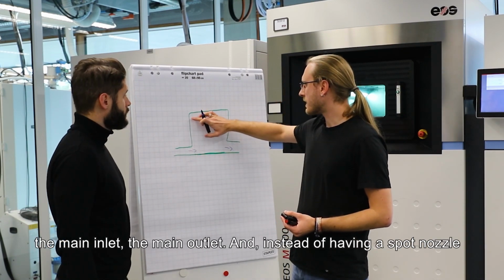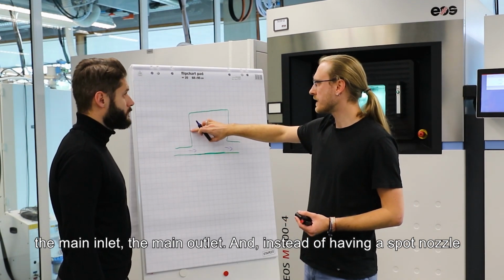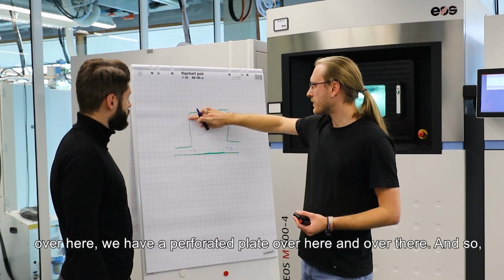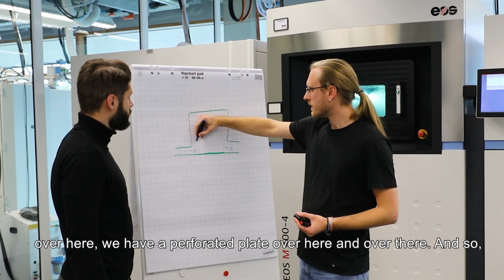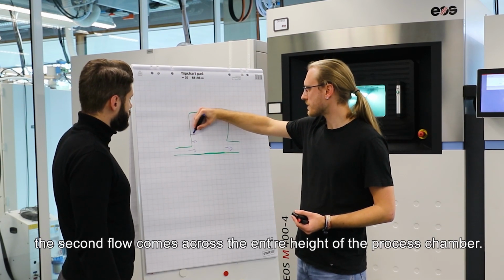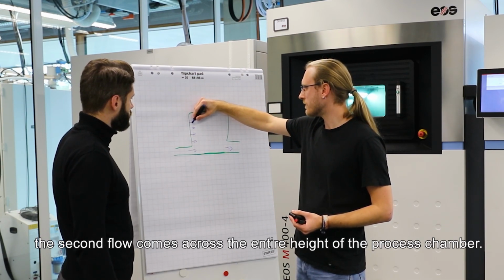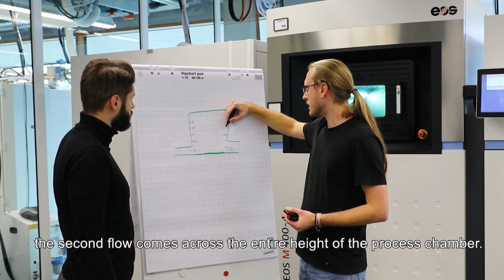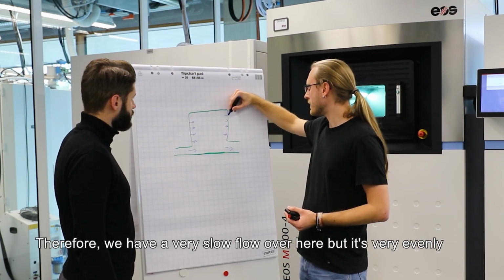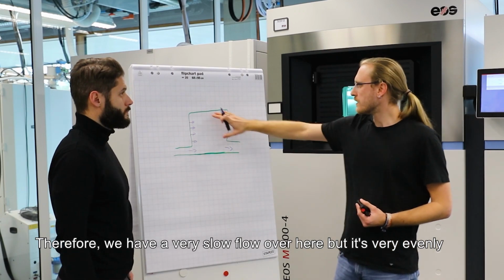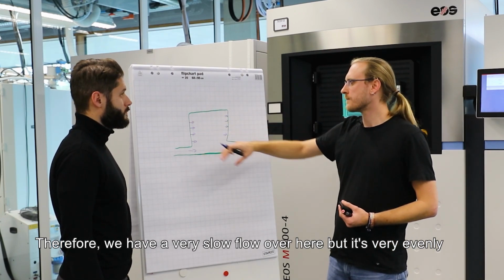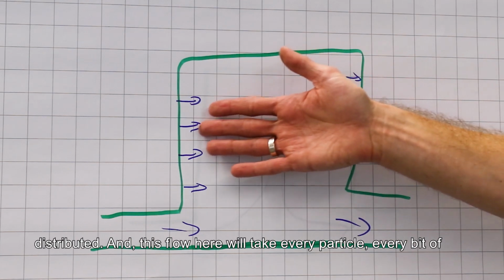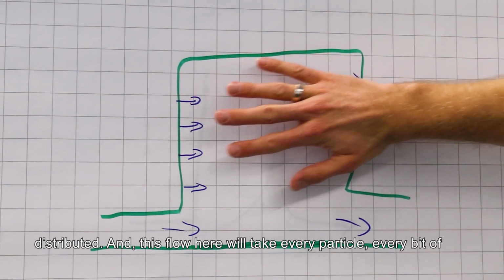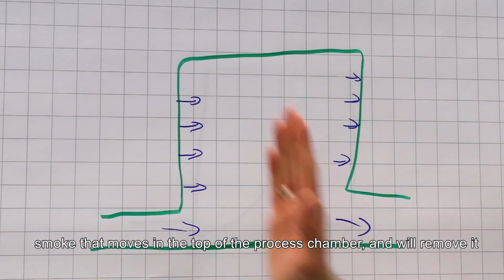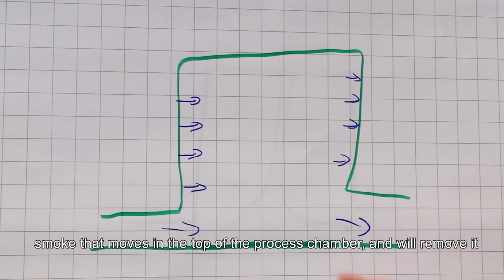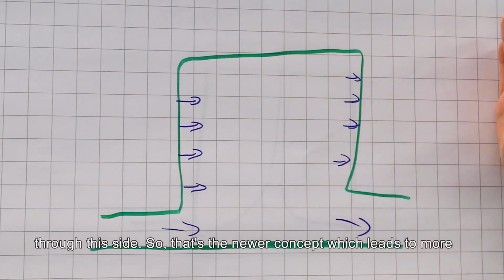And instead of having just a spot nozzle over here, we have a perforated plate over here and over there. And so the second flow comes all over the ceiling. So therefore we have a very slow flow over here, but it's very evenly distributed. And this flow here will take every particle, every bit of smoke that moves in the top of the process chamber and will remove it through this side.